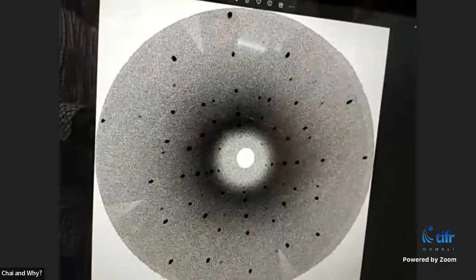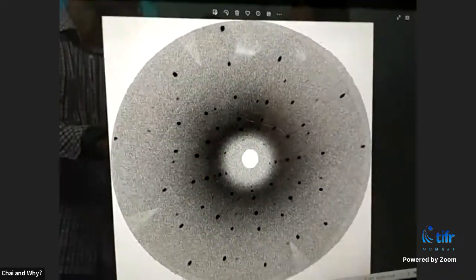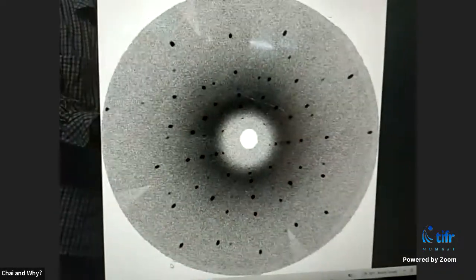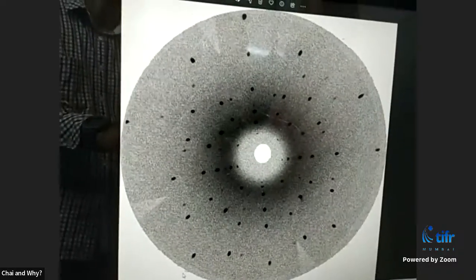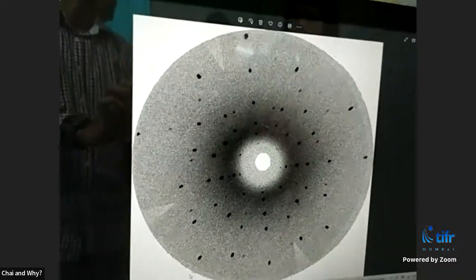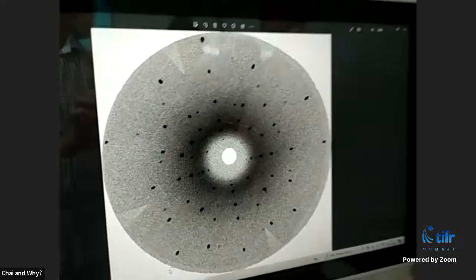If the spots are a little bit elongated or ellipsoidal, then there may be some sort of defect. One needs to do some kind of annealing to get rid of this thermal shock and all these things. So it's important to get a well-defined circular pattern. That indicates a good quality single crystal.